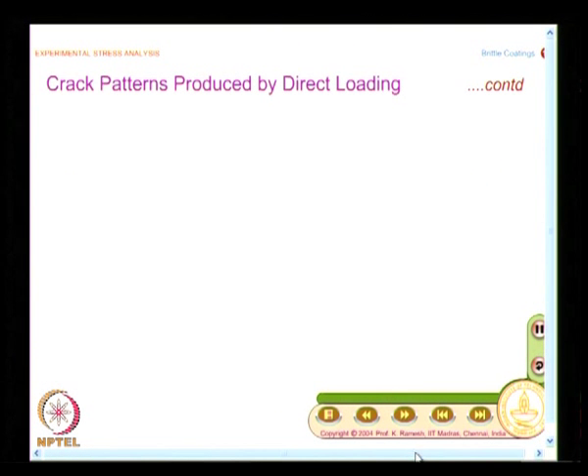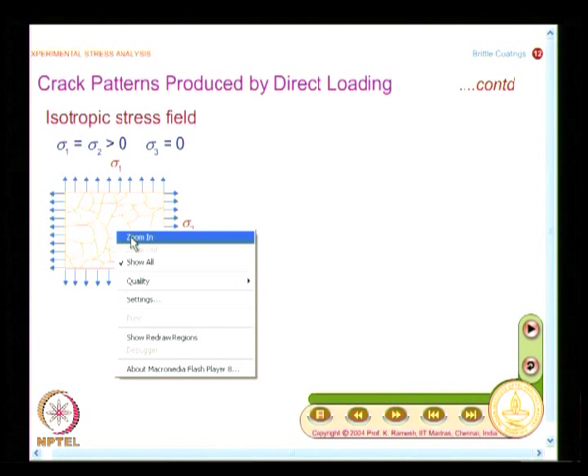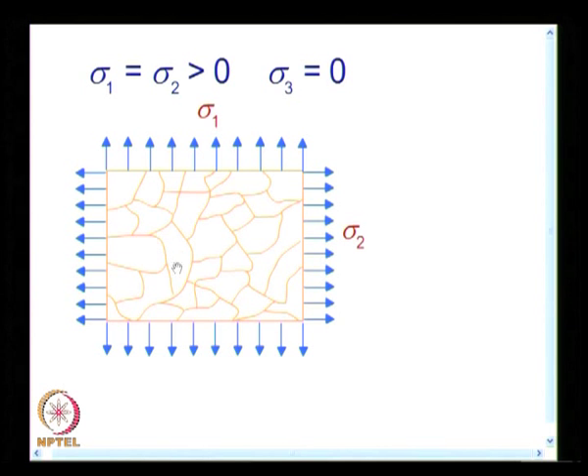When the principal stress magnitude is the same in every direction — called an isotropic field where σ₁ = σ₂ > 0 — you get random crack patterns. If you come across random crack patterns in whitewash on buildings, you can immediately conclude that the principal stress direction is the same in every direction in that zone. For the case of a ring under diametral compression, the thick lines are isoentatics, the thin lines are isostatics, and a random pattern is visible at the isotropic point, indicating an isotropic stress field where every direction is a principal stress direction.